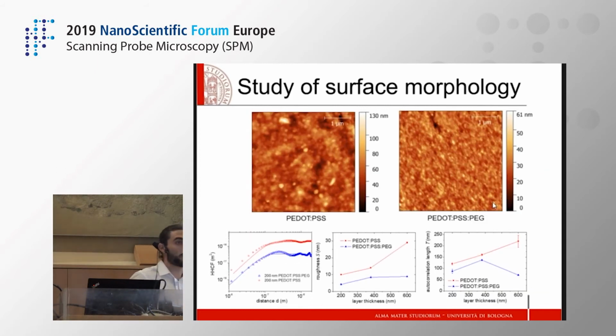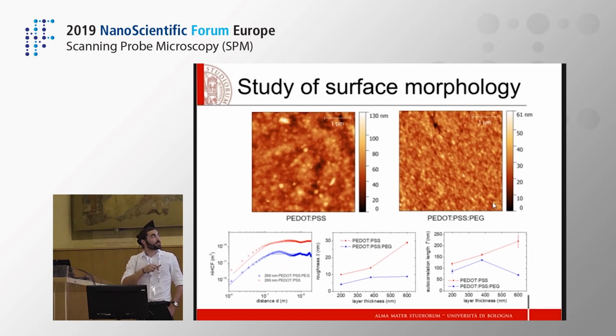We studied the morphology of PEDOT:PSS and PEDOT:PSS PEG, and fitting the height-height correlation function, what we obtain is that roughness and autocorrelation length reduce when we introduce the PEG in our mixture. In particular, for PEDOT:PSS, the roughness and correlation length increase for increasing thickness, and the PEDOT:PSS shows the typical cauliflower structure. On the other hand, for PEDOT:PSS PEG, this behavior is no longer present, and we have almost a constant value for the two parameters, and also smaller structures in the film itself, probably due to an altered growth mechanism during the deposition.